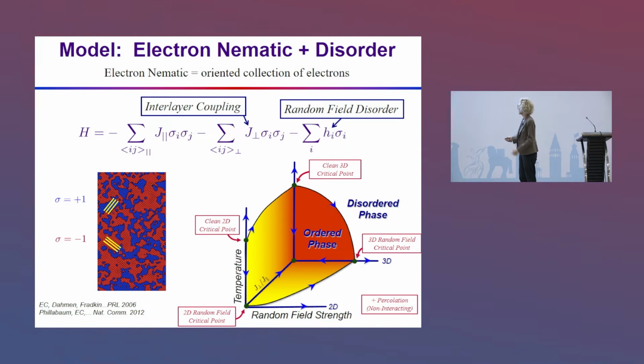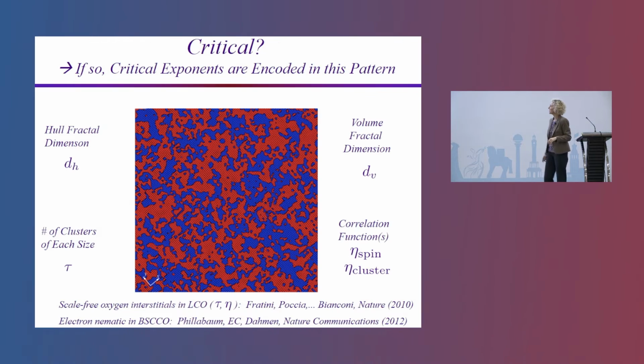What are the controlling critical points? So the blue arrows on every phase transition line tell you which way you need to look for the fixed point that's controlling the critical behavior of that line. And so we have a few different fixed points here. We can be in the two-dimensional limit or in the three-dimensional limit. We could be in a limit where disorder doesn't matter for the pattern formation, or we could be in a limit where disorder matters. Or maybe things don't interact at all. Maybe this pattern formation is just a flip of a coin at every region of space on the surface of the sample. Maybe it's not interacting. So we include these 5 fixed points in our analysis.